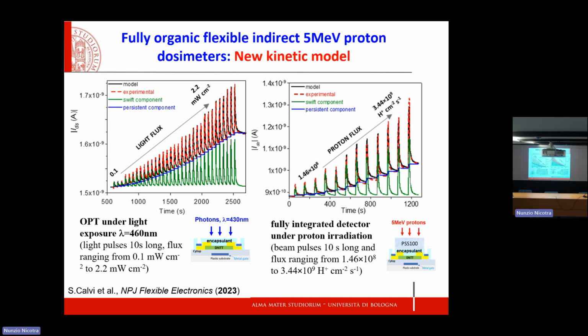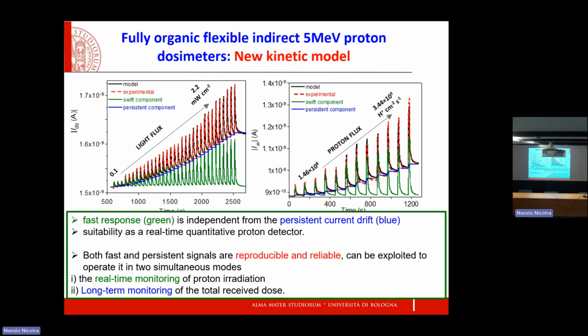And the message would be, so why not use, instead of an organic phototransistor, another type of semiconductor that allows you to have a faster response and avoid this kind of slow component that stays? Well, the answer is yes, if you find a material that can be deposited by printing over large area and maintain flexibility, okay? So you can't have everything always at once. But what is really nice is that by understanding the origin of this curve, we can definitely control and use it as a quantitative, calibrated tool, to measure the dose of protons actually received onto the device.